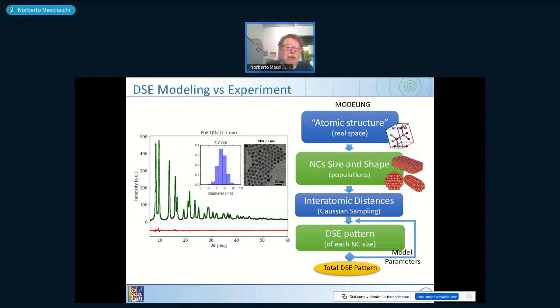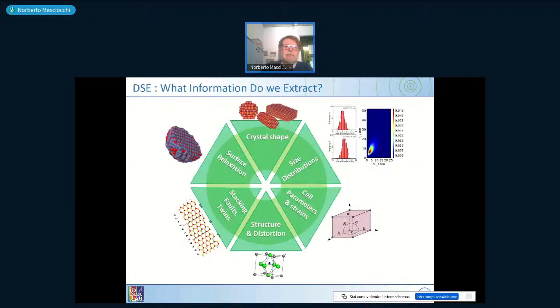And after all, the method we are using here is very general. So the information we can extract from such a method is shown here in this hexagon. Starting from the top, you can get information on crystal shape. That's something that normally is overlooked in the normal structure refinement for single crystal powders. You can get not only the average size, which is obtained as a fallout of a refinement, but you can get size distribution not only in one direction, but in two directions.